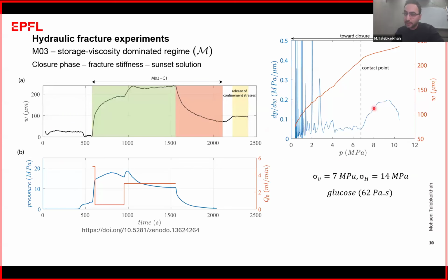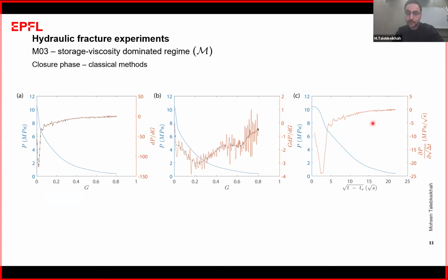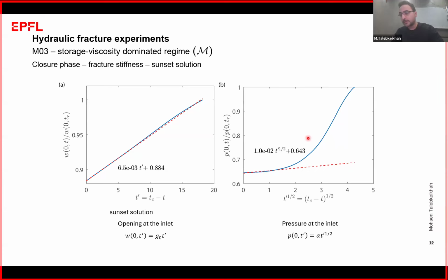So we have the peaking point, we have the peaking pressure, and we have the contact pressure and contact time. So we can check the sunset solution that Pierce and Detournay developed, and we could easily see that the opening asymptote is really linear where it is the time of the full closure. And we can see that opening at the inlet of the fracture has a linear relationship with the reverse time. And also here we can see that opening has a residual opening, and this offset is because of that residual opening. And also for the pressure asymptote of the sunset solution, we can see that the pressure at the inlet of the fracture has a linear behavior with the square root of the reverse time. And this is interesting because we could see the analytical solution in our experimental results.